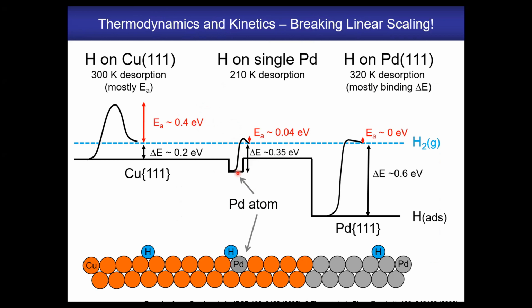And then you actually have weak binding to the hydrogen atom, because the hydrogen atom bonds mostly to copper rather than to palladium because it sits in a threefold site. So it means where it sits has a binding strength more similar to copper than to palladium. And it's also so weakly bound it can spill over onto the copper surface, which I'll show in a minute. So here we're showing for hydrogen dissociation for a palladium copper single atom alloy, we've broken linear scaling because we have both things we want.